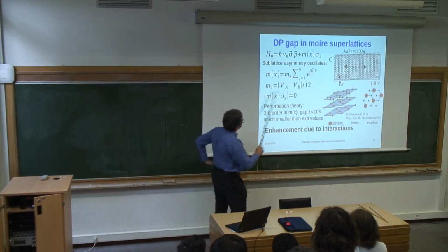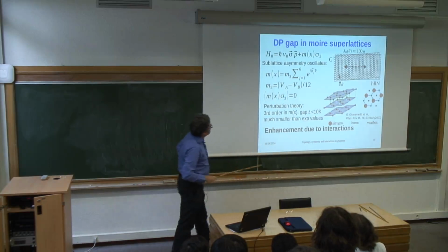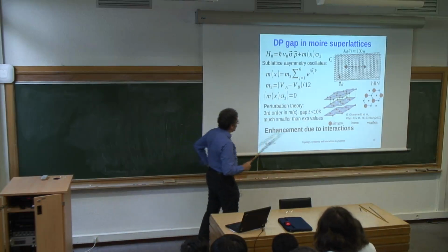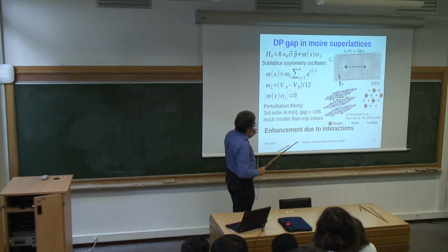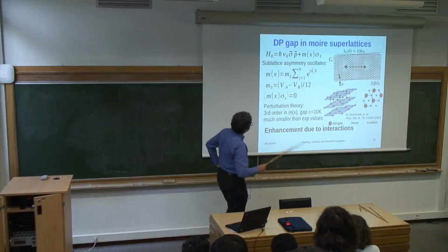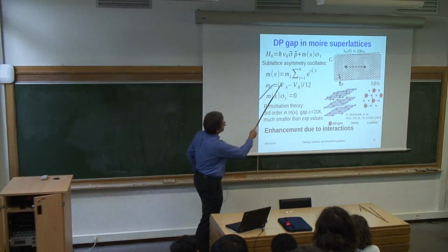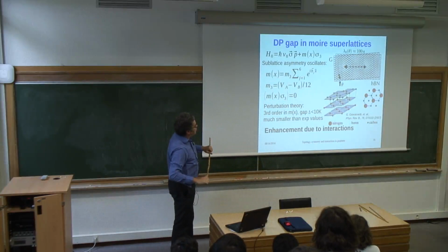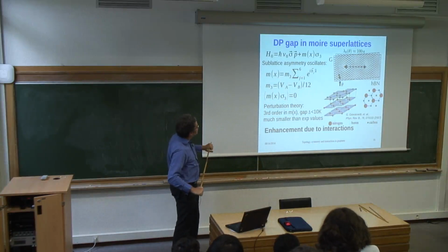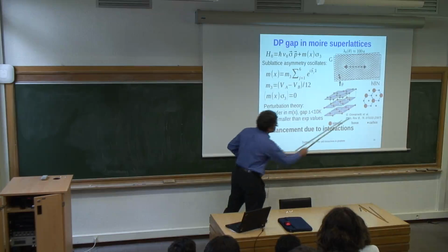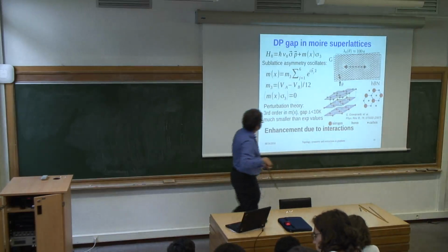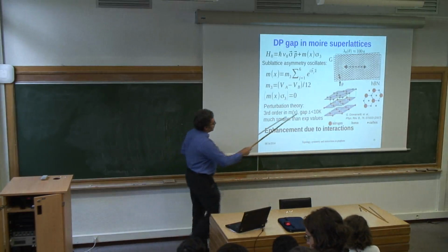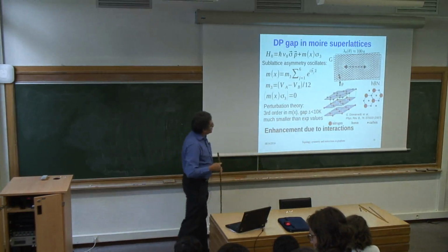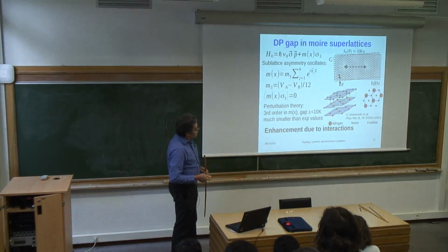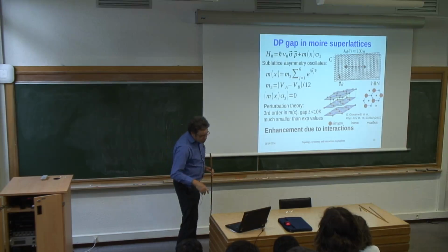And so you need to go to third order in this M3 parameter to get a gap, and because of that you get suppression compared to the first order value, and so the gap, even if you take the M3 value of order a few hundred Kelvin, which is predicted by ab initio, for example in this paper and other papers, then at third order you get a gap which is about 10 times smaller than the experimentally observed values. So to explain this enhancement,